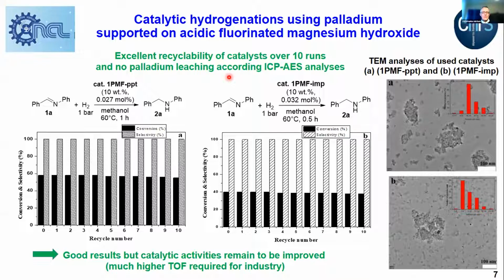Over 10 runs, there was no palladium leaching according to ICP analysis, and the TEM analysis of the catalyst after recycling was really clear. We had no aggregation of the catalyst, and particle size was not modified. So overall, good results were obtained. However, the drawback is the catalytic activities, which remain to be improved because we did not have so high turnover frequencies. So for industry applications, it remains to be improved.